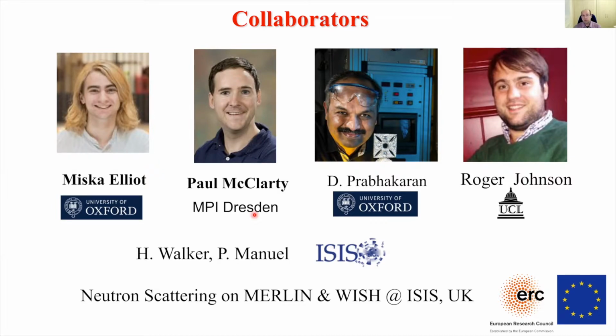The crystals were grown by D. Prabhakaran in Oxford using an image furnace indicated in this image here. And Roger Johnson focused on analyzing powder neutron diffraction measurements to understand details of the magnetic structure. And these were important to relate back to the spin and orbital magnetic ground state of the ions relevant for this material. The experiments were done using the ISIS pulsed neutron source in the UK, powder measurements by Pascal Manuel using the WISH instrument, and the inelastic measurements we did on the instrument MERLIN in collaboration with Helen Walker. And this research is sponsored by a grant from the European Research Council.